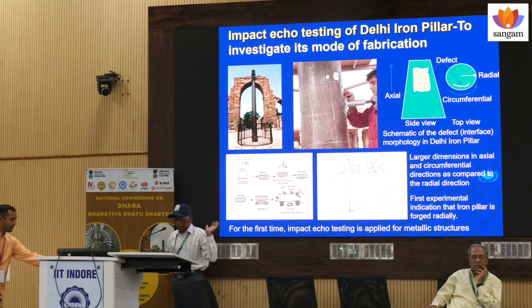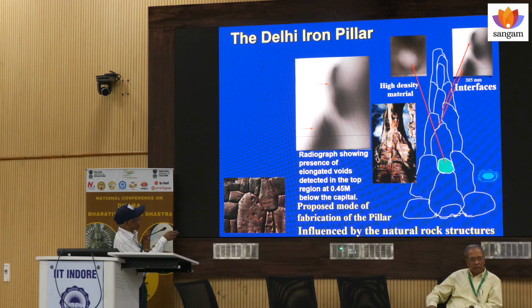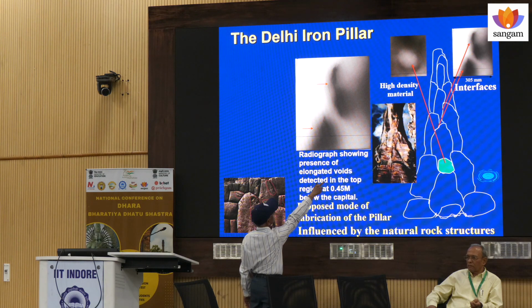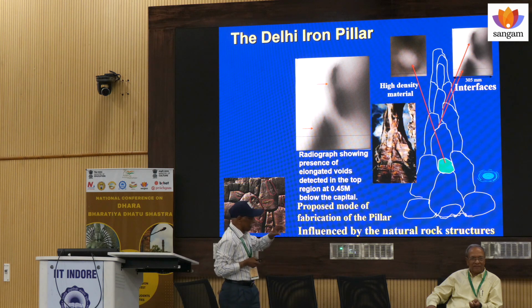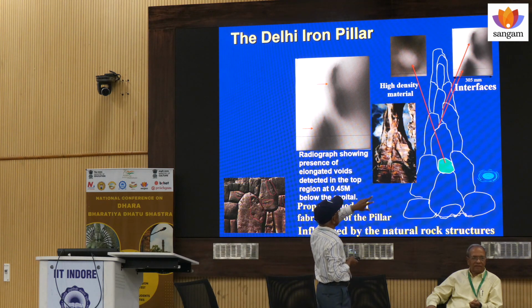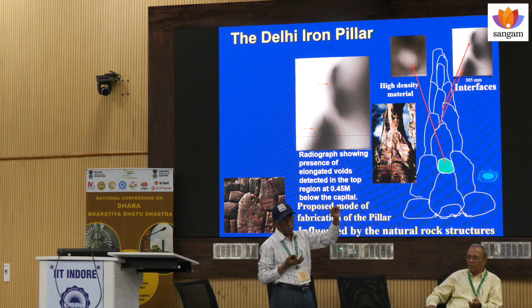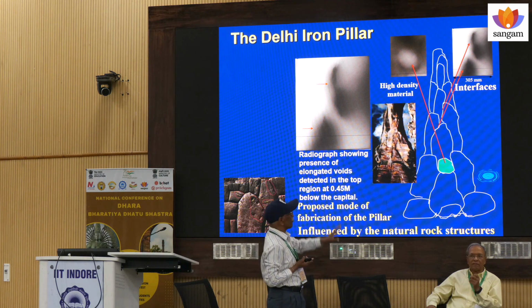So when you do the radiography, you can see the orientations of the interface, this is in the axial direction of the pillar, you see that these are all axial and circumferentially oriented. If the interface is not like that, you won't see the contrast from the radiography. That is one aspect. And then in one of the regions of the iron pillar, you can see that the white contrast in the radiograph means the metal is heavy compared to the remaining regions. That's why X-rays are absorbed in that region, because X-ray absorption is directly related to the atomic weight. So we believe that there is some material which is denser than the iron.